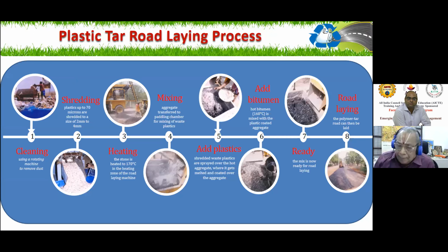Now, this is done. I hope I can go up to 11:45. I hope I understand from the chart. So the very simple thing is, you take the plastic and clean it, and then add it over the stone, laminate it, and then add the bitumen and mix it and get the road. Simple. Take the stone, heat it to 170 degrees, add the shredded plastic as I told you. This is the shredded plastic which is taken. Add this over that. It gets laminated. Add the bitumen. Mix well. You get the road. Beautiful road you get.